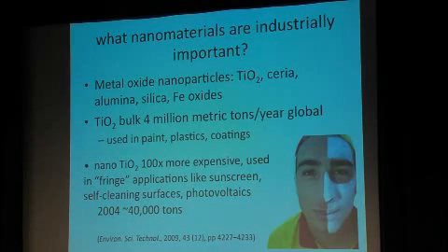But there are applications where, when you make the particles of titanium dioxide smaller, you get new functionalities. We saw earlier that the absorption spectrum of titanium dioxide shifts when it becomes nanometer sized, and that's used now in applications like invisible sunscreen. For example, here this gentleman has half his face with a zinc oxide type sunscreen. But you can now get sunscreens where you put sunscreen on and you don't have a mask on your face.